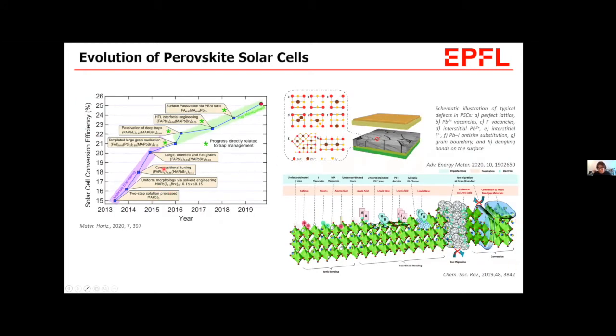This chart well summarizes how perovskite solar cells have progressed. The works that I introduced were mostly about material engineering with the evolution of device configuration. Perovskite was already an ideal material for solar cells, based on excellent properties like absorption coefficient, long carrier diffusion lengths, high defect tolerance, etc. So you could focus on optimization of the materials and processes. But from this point, 21% to 25%, it has been mostly based on the management of traps. A trap is actually a defect. So defect engineering becomes important to improve efficiency further.